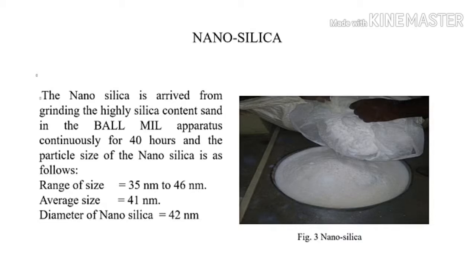This is an example of nano-silica. The nano-silica is derived from grinding highly silica content sand in the ball mill apparatus continuously for 40 hours, and the particle size of the nano-silica is as follows. The range of the size was between 35 nanometer to 46 nanometer. Average size was found to be 41 nanometer, whereas the diameter of nano-silica was 42 nanometer. The image shows an example of nano-silica.